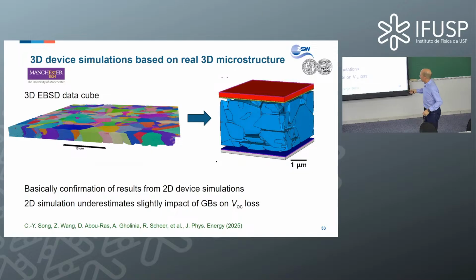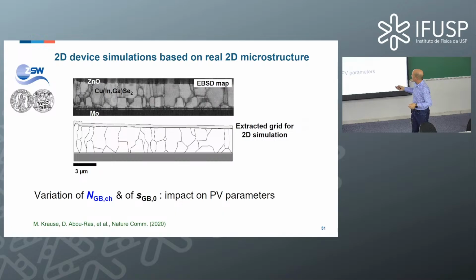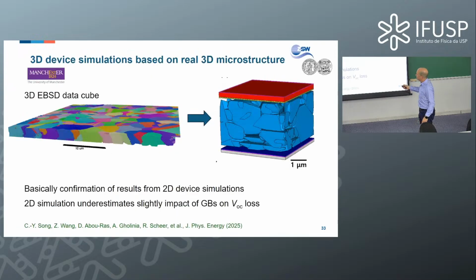simulation. And basically, we get a confirmation of the results that we get from the 2-dimensional device simulations. There's a slight underestimation of the impact of grain boundaries on the VOC loss by the 2-dimensional simulation. It's simply a geometrical issue. You cannot just assume, oh yes, more or less, you can rely on one section that you look at. It's simply not getting close to the real world that we can actually find here.